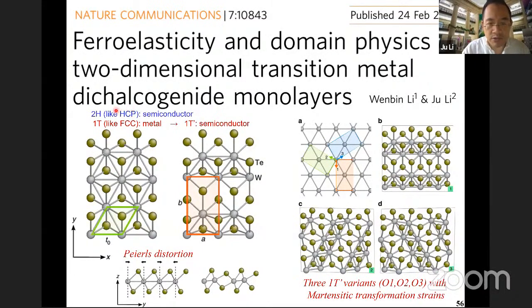It's like a hexagonal close pack structure. And that's a semiconductor. But the T structure is like the FCC structure where you have the inversion symmetry about the middle plane transition metal atom, but you don't have the mirror symmetry. Now, the T structure turns out to be unstable, and it will undergo this Peierls reconstruction to this half reconstructed structure called 1T prime structure. That's also a semiconductor.